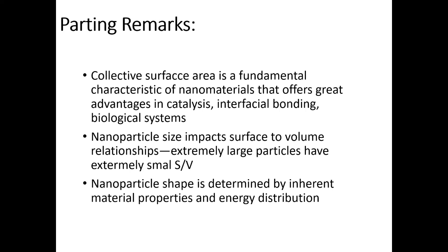The scratch resistant coating is using nanoparticles, not micron-sized particles. Not only that, micron-sized particles scatter light very strongly, so you may be losing some of the clarity that you want under a clear coating. So interfacial surface area is very important in polymer chemistry, especially when it involves putting in carbon nanotubes or silicon nanoparticles or zinc oxide, things like that.